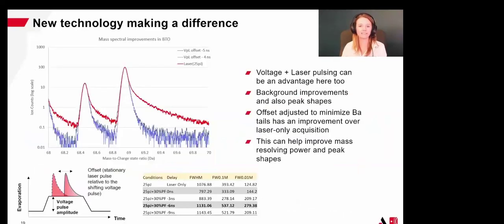So finally, the last thing that can really help us out here with new technology in the analysis of MLCC materials is simultaneous voltage pulsing. This is technology available in the LEAP 6000 XR, and what that means is essentially pulsing with a voltage and laser pulse simultaneously. So these are synced together to hit the sample with both a laser and a voltage pulse at the same time. Now, the primary goal of this is to reduce the background noise. As we already talked about, this is already quite low in the MLCC ceramic materials with deep UV, but there's always improvements that can be made.